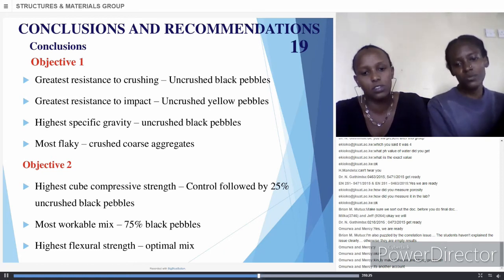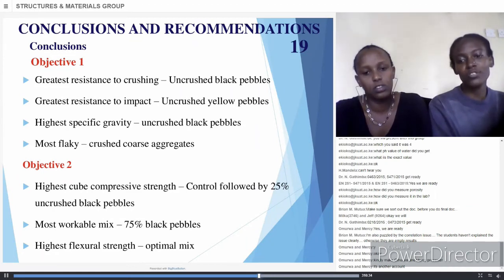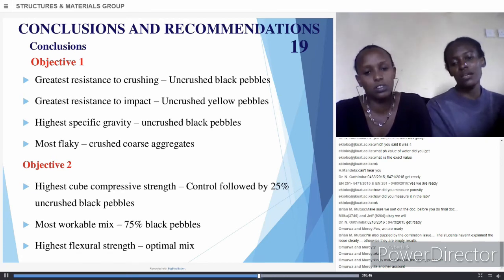On to the second objective, the combination with the highest cube compressive strength was the control, closely followed by our optimal mix, which was the 25% uncrushed black pebbles. The most workable mix, the one with the highest slump, was the 75% black pebbles, and the mix with the highest flexural strength was the optimal mix.